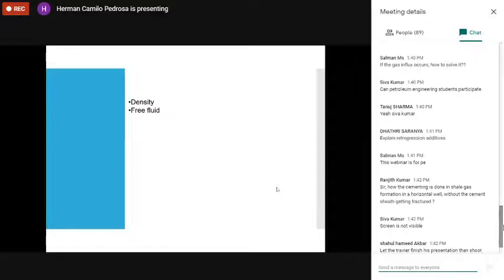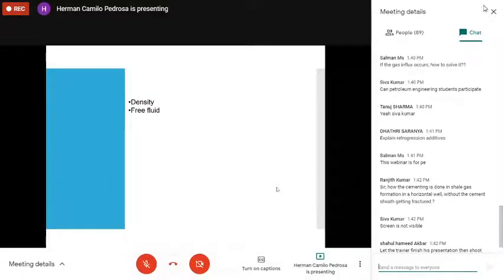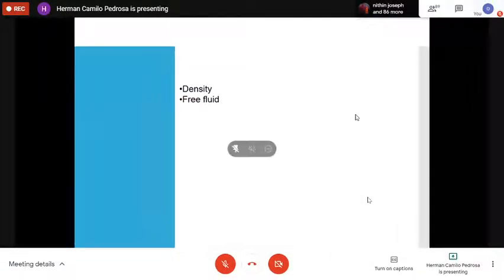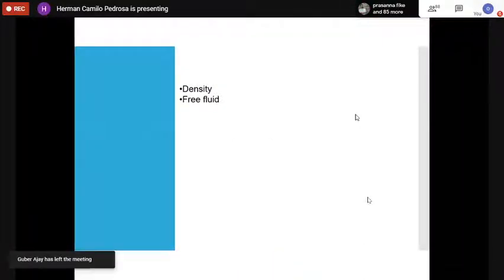So that's very important. And we do it with a regular mud balance that I guess many of you know. Also, what we control is free fluid. The free fluid is the water that appears if the cement has sedimented and we have some water on top. If we are cementing a vertical well, that can be an issue, because the top of cement won't be as high as we want, but it maybe won't be so problematic.